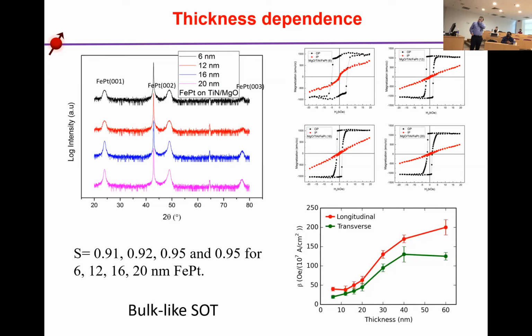In order to rule out the interface effect, we have done the thickness dependence, with thickness up to 60 nanometers. But for this kind of material, we have to make sure the chemical order degree is kept the same. The chemical order is defined by how well the atom layers are aligned along the C direction. For all the thicknesses, the chemical order is quite similar, and they also maintain very good perpendicular anisotropy. We can see the effective field due to the SOT increases with the thickness. Therefore, we say this SOT is induced by the bulk, not from the interface.